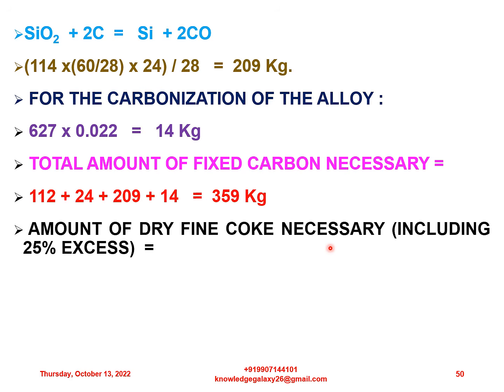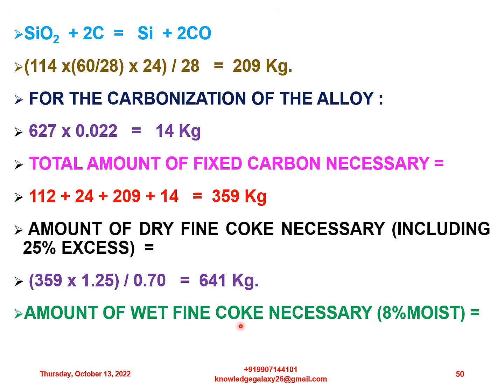The amount of dry fine coke necessary including 25% excess is equal to 359 into 1.25 divided by 0.7, which is equal to 641 kg. 0.7 is 70% fixed carbon of the coke. Next, the amount of wet fine coke necessary having 8% moisture is equal to 641 divided by 0.92, which is equal to 696 kg. My dear friends, don't get confused with these two different quantities, as 641 is the dry coke quantity and 696 is the wet fine coke quantity. They are two different and separate quantities.